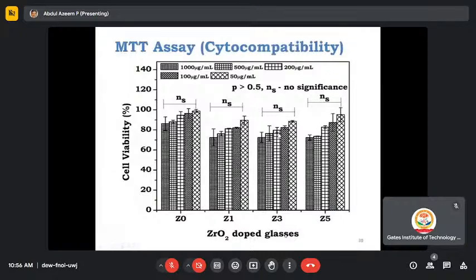And then with this formula, we are going to check the viability of the cells. You see here, these bar graphs, if you observe carefully, the viability of the cells in all the compositions is above 70%. If you see this, it is 80, and in some cases it's 100. So it is 75 to 90. Z0 means without zirconium, Z1 is 1% zirconium, Z3 is 3% zirconium, Z5 is 5%. So with increasing zirconium, we observe that the viability is above 70.